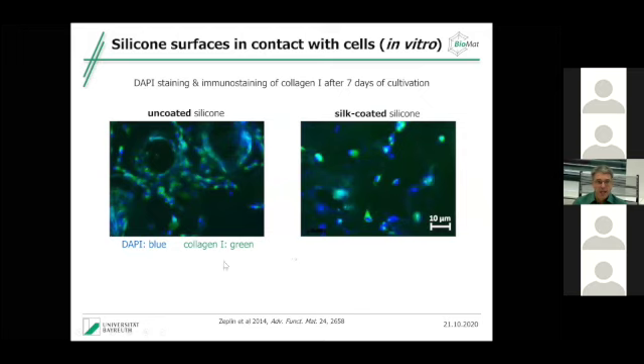Here you see what happens with the cells, and here we just had some DAPI staining, which stains the cell nucleus, and some collagen-1 staining after 7 days of cultivation. Uncoated silicone, you see that here the fibroblasts grow, they have a lot of collagen production. The silk-coated silicone, as before, they're not even spreading out, they're not proliferating, they're not making collagen. And this is the explanation why we don't get capsule formation and we don't get fibrosis.